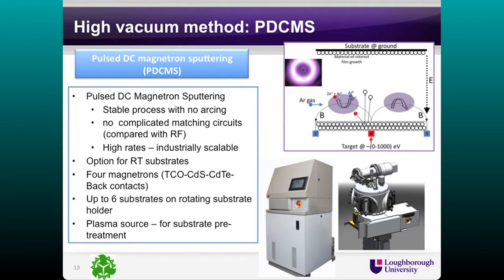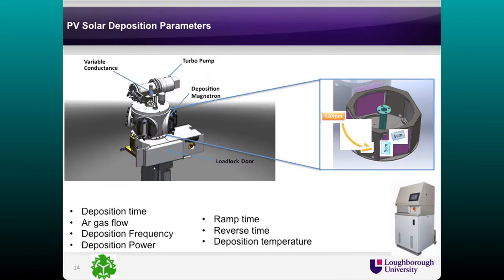We can think about an inline process, so by using just this machine that you can see here, we can produce the whole device: the front contacts, the layers that we need to obtain the device, and the back contacts. We can load different substrates, and we can even use a plasma source for substrate pretreatments. So we can control different parameters like deposition time, the gas that we're introducing, frequency, power, and temperature.